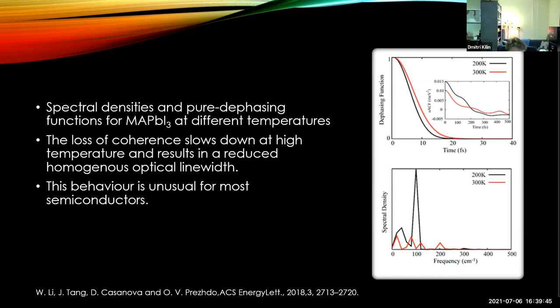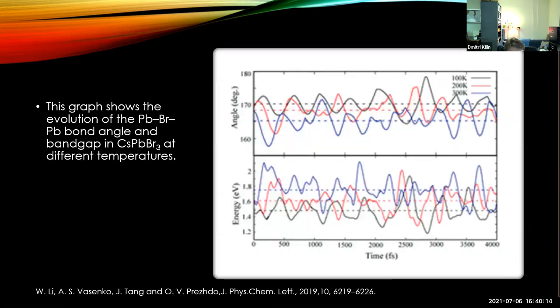So it is expected that at temperatures above room temperature, above 300 Kelvin, the angles between bromine and lead are either 90 or 180 degrees, so it is ideal cubic. And as one pulls the temperature down, it starts deviating from right angles. So maybe Aaron saw the previous slide with angles wiggling around and concluded that it is a signature of a phase transition.